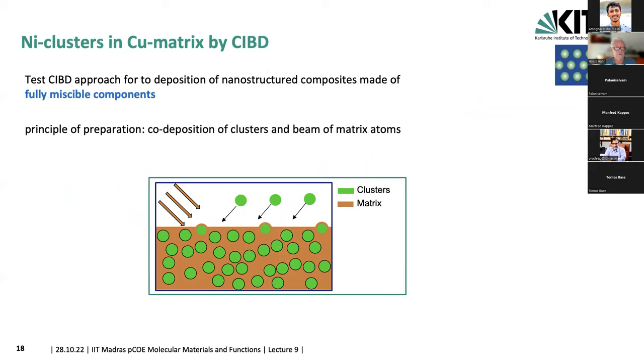So in order to test the capabilities of that system, the co-deposition of clusters and of the matrix, I asked my student Gleb Jankovic to test it using a fully miscible system. There are several systems which we had in mind, but this one, nickel and copper, is really the standard system that every materials scientist knows for full miscibility. And because nickel is, of course, ferromagnetic, we can also use magnetic measurements to learn about the cluster size and the cluster size distribution. So this gives us, in addition to other techniques which I will show you, an additional property-related technique to look at the clusters.